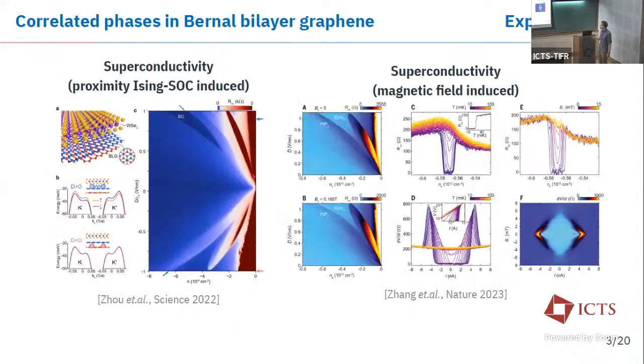Now, other experimental discoveries, of course, include superconductivity, and this is also one of the main points of focus for this material. So far, superconductivity has only been discovered when inducing some kind of magnetic or Ising spin orbit coupling into the material. On the left, you see Bernal bilayer graphene put on top of a tungsten diselenide substrate, and the induced Ising SOC leads to a superconducting region in one part of the phase diagram. On the y-axis, you have, again, vertical displacement field. On the x-axis, you have hole doping, and the phase diagram is asymmetric because the setup is asymmetric. You have on one side the WSe2 that induces spin orbit coupling, and on the other side you don't. So only for doping carriers into the direction of the WSe2, you actually see this superconducting phase.